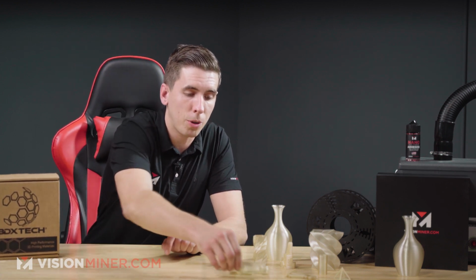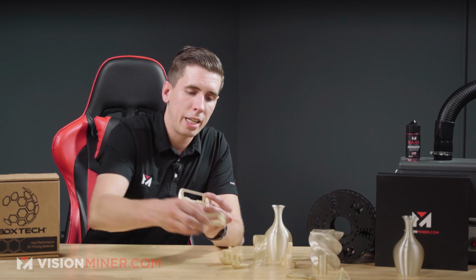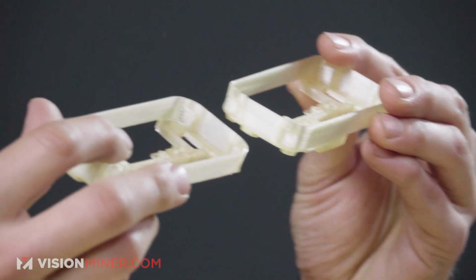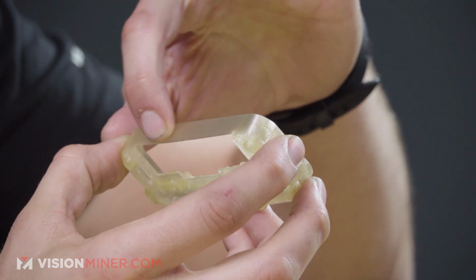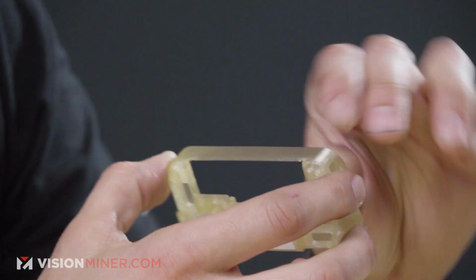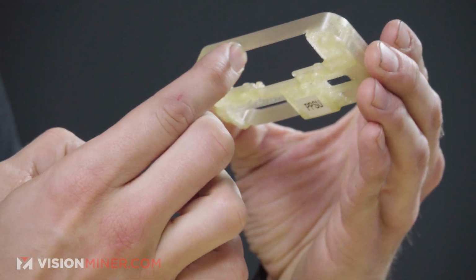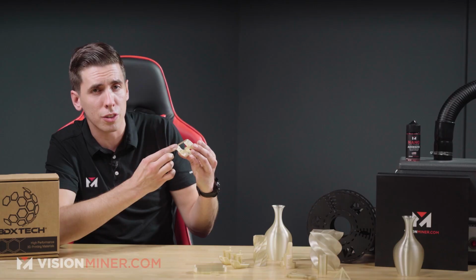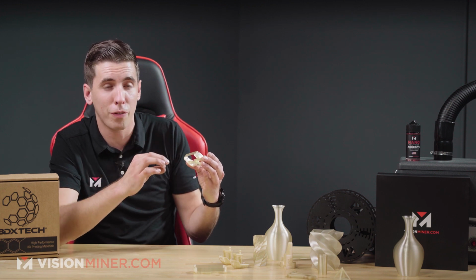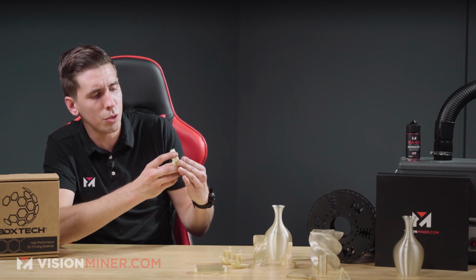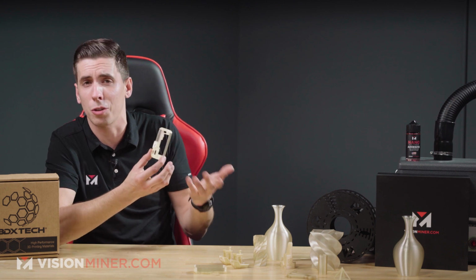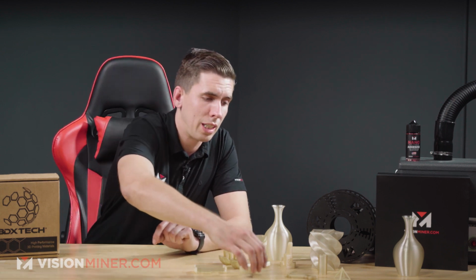Now we've also got these parts, which are electronics enclosures. And if you look really closely, you can see the warping actually happening over here. Now we did use a little bit of support. These are printed with a 0.4 nozzle, 0.2 millimeter layer height, and one layer of separation for the support. And you can see the bottom surface is actually pretty good. Sometimes it's nasty, sometimes it's perfect. This one's sort of in between. So you can do a lot using supports. This is an electronics enclosure, very, very cool stuff.